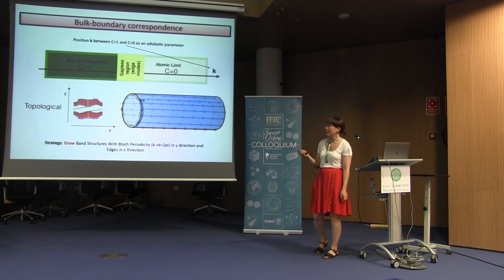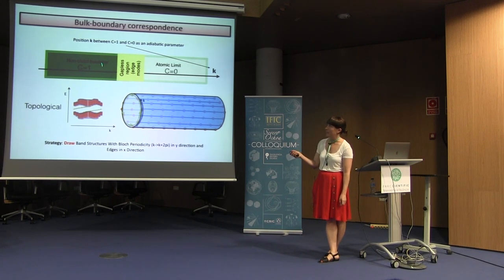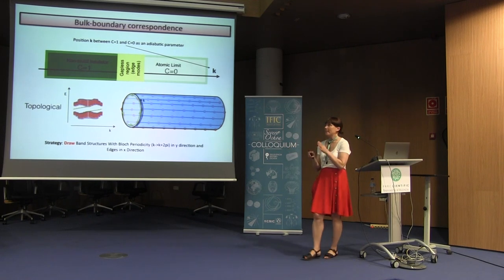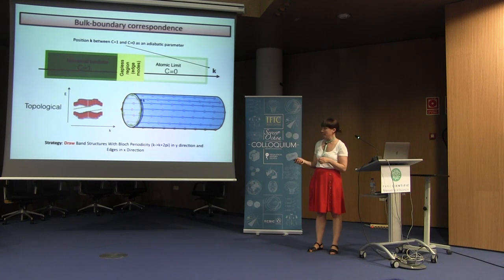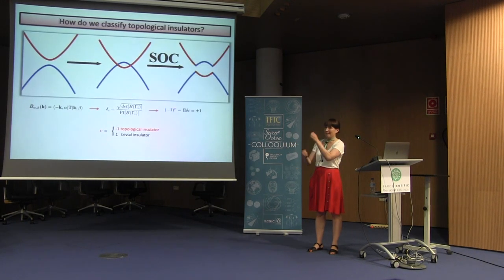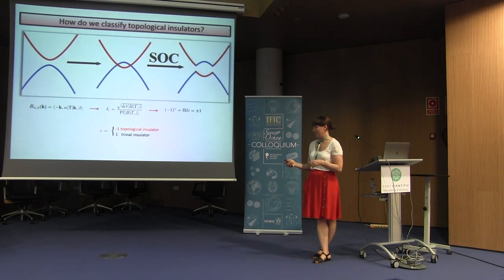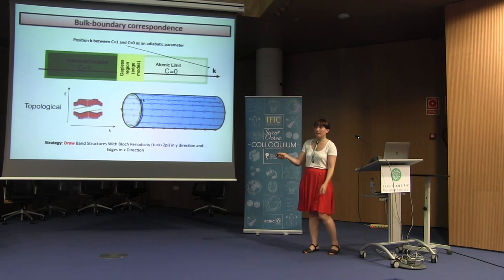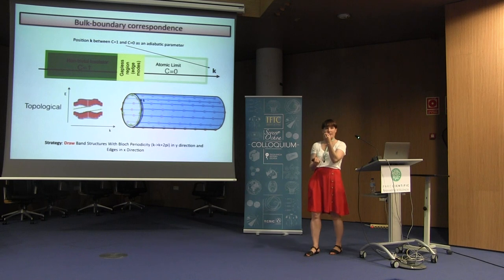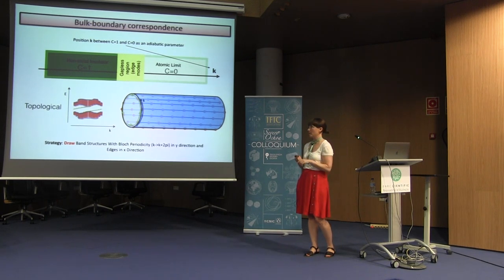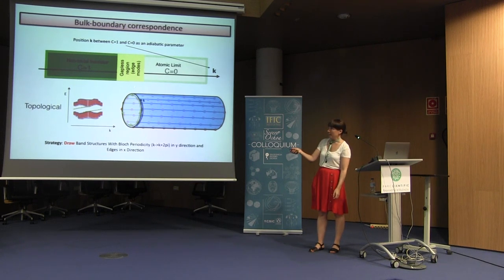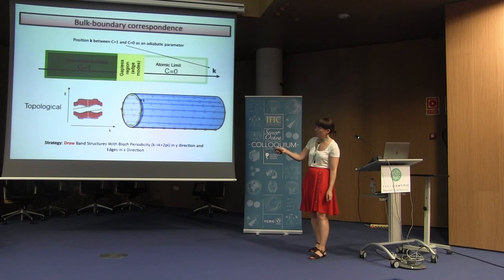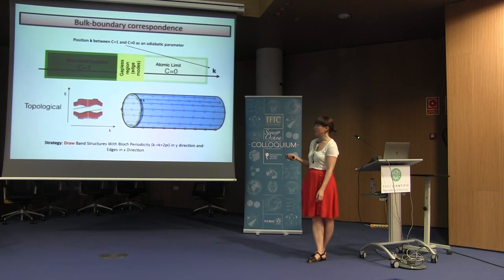And an easy way of understanding it is if we have a non-trivial insulator and we interface it with a trivial insulator, which is, for example, vacuum, what happens is that our inversion of the bands needs to be uninverted, because this inversion only happens when we have a non-trivial system. When we have a trivial system, the bands recover their natural order, let's say. So in this natural order, what happens is at a point the gap closes, and at this point where they close, we have an edge point. We have a surface state, and in this gapless region that is actually very small, we have conductivity.